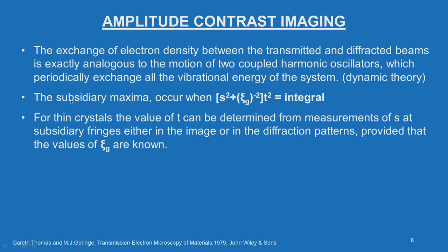These two equations explain the interaction of the transmitted beam and the diffracted beam. The exchange of electron density between the transmitted and diffracted beams is exactly analogous to the motion of two coupled harmonic oscillators, which periodically exchange all the vibration energy of the system.